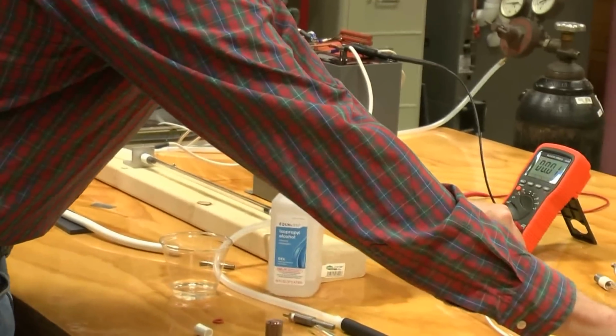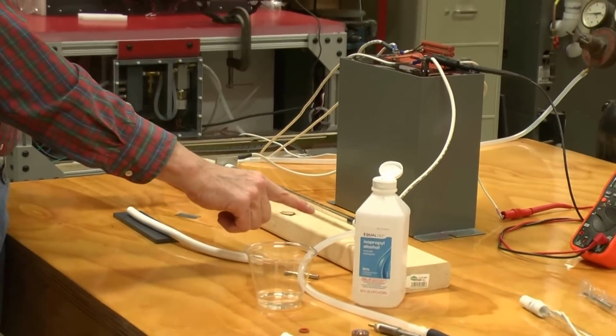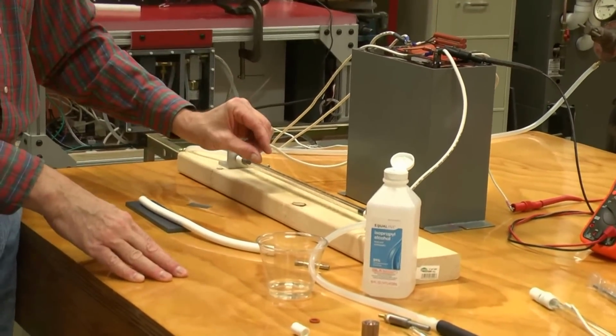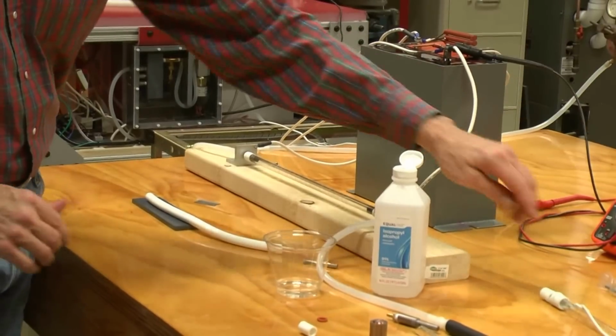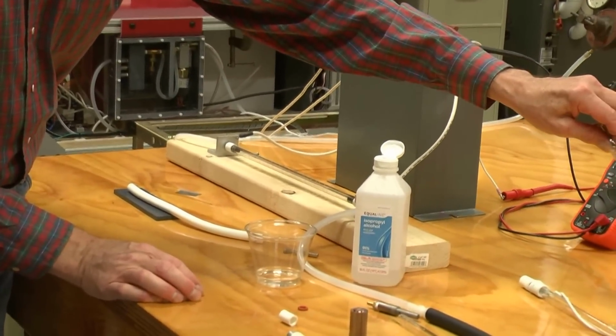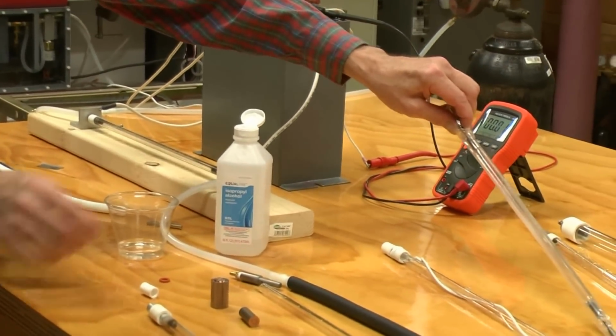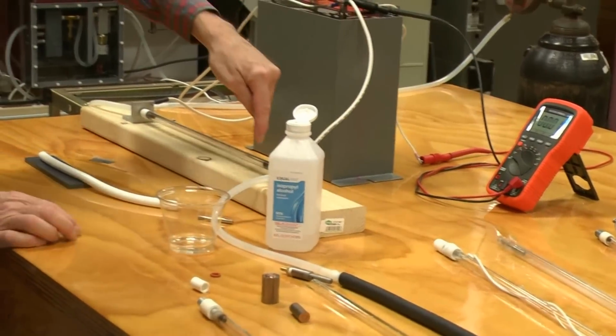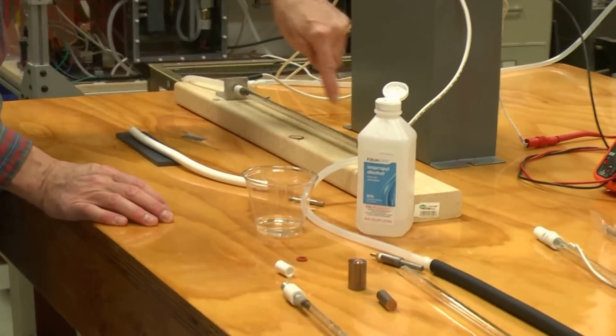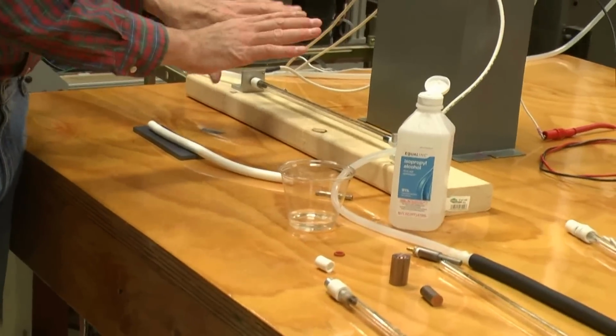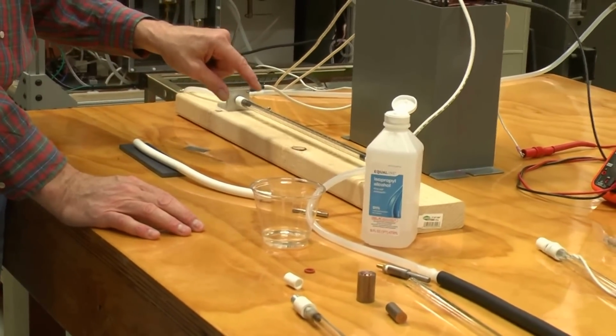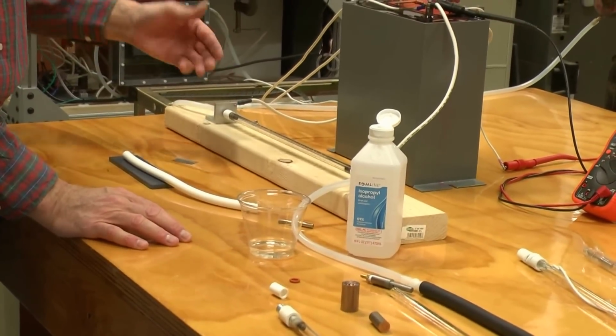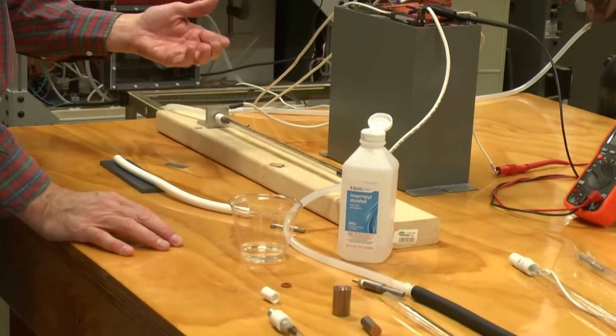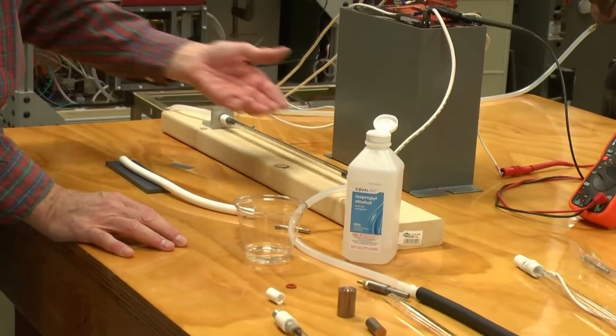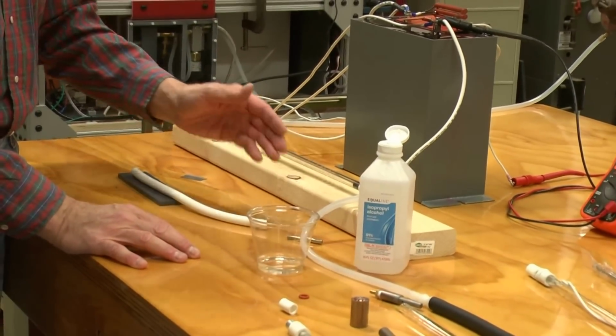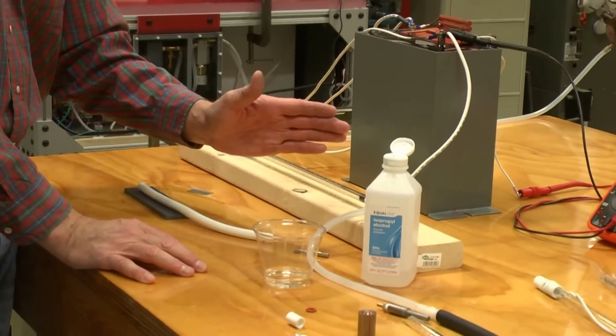If I do the same thing with this low pressure lamp that is actually narrower and longer than the lamp that I have here, this is an 11 millimeter ID by 27 centimeter electrode spacing. This is an 8 millimeter ID by 33 millimeter electrode spacing. It should be slower, but it discharges in 15 microseconds. The reason is that its pressure is about 10 to 15 torr. It's about 20 or 30 times lower pressure, very low impedance, and as a consequence, very fast discharge.